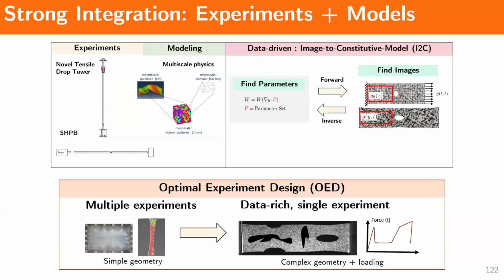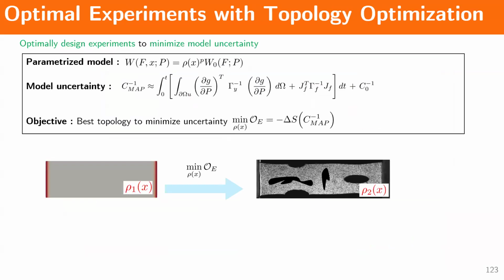Now, you can also look at it from a Bayesian perspective, and this allows you to get some uncertainty of the inferred model. In particular, you can get a quantitative expression of your inferred model uncertainty, and this allows you to do quantitative optimal experimental design, where you ask, what's the best topology or the best geometry that can minimize the uncertainty in the model that we can then infer. So now we're working on this optimal experimental design with topology optimization methods to get the density field here that can minimize the uncertainty of the model that we will infer before seeing any real experimental data.